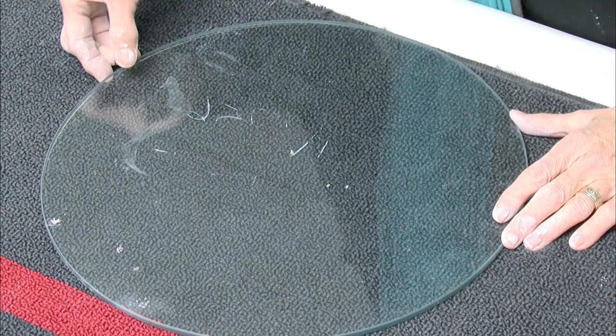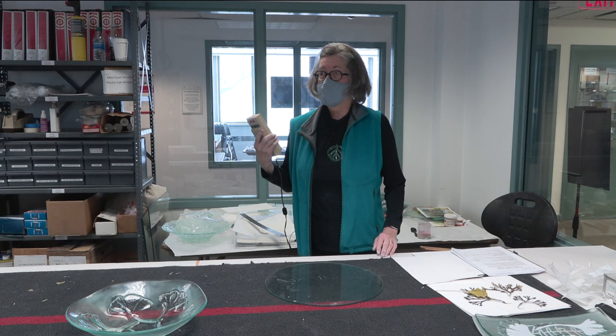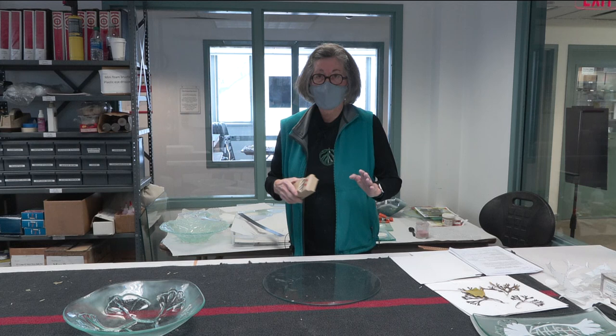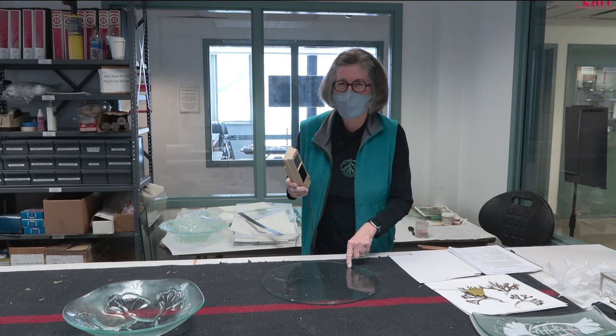Well, we use a tin scope, and it's a UV. Use a UV shortwave, not long wave. Long wave is black light. That's 365 nanometers. Shortwave is 254. So I'm going to turn this on. You can buy smaller tin scopes, they run about $80. Some people say you can taste the tin side because it has a metallic taste. I haven't gotten that to work.